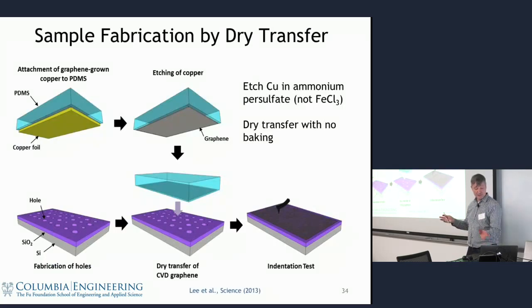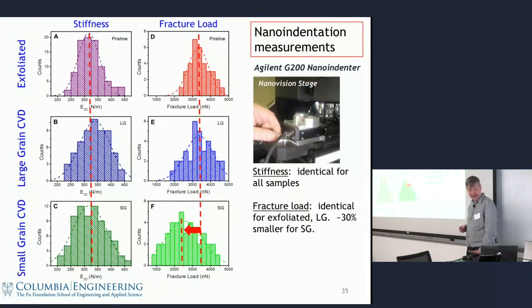We also did some work to eliminate or just clean up the processing as much as we could. We did a dry transfer process, which helped things as well. The last thing we did is we've actually shifted over from doing all of our work in an atomic force microscope to using a nanoindenter.